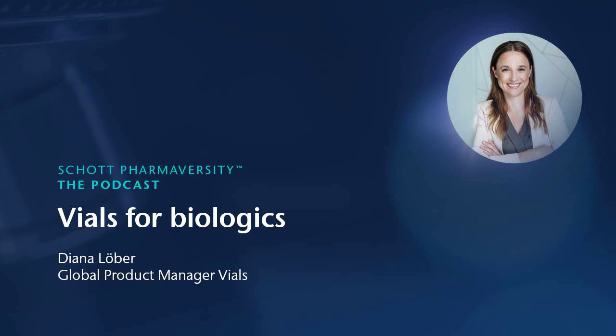Yes, of course. So, for example, we noticed that there are more and more biologic drugs which use buffers in the higher pH range. And this is a challenge for standard borosilicate glass vials that are the common standard for parenteral drugs. And borosilicate glass is a well-known, proven, reliable material, and it provides stability for the drug over shelf life. Yeah, but when it comes to pH higher than around 7, a hydroxide ion attack takes place. And this attack is continuous and dissolves the silicon-oxygen bonds of the glass network, releasing network modifier elements into the solution. And these leachables might have an impact on the drug, resulting in denaturation of protein, aggregation, or even deactivation of the drug. And this, of course, is something that needs to be carefully evaluated.